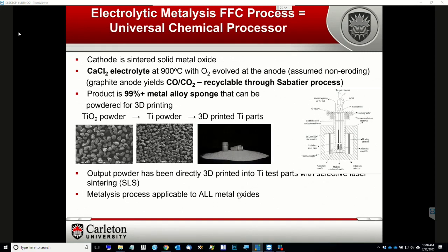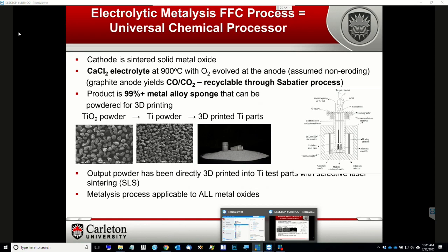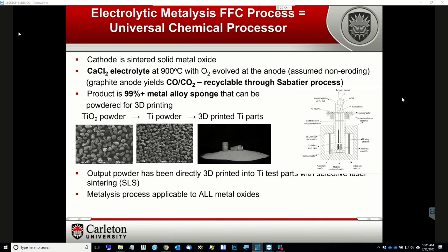So the next process is to take the minerals that we have and then reduce them. Now the Metalysis FFC process is a very powerful technique, essentially a universal chemical process. It takes a calcium chloride electrolyte. It operates in the solid state. There's no melting. It has low temperature operation, about 900 to 950 degrees C. Oxygen is evolved at the anode, and the product yielded is greater than 99% metal alloy sponge.